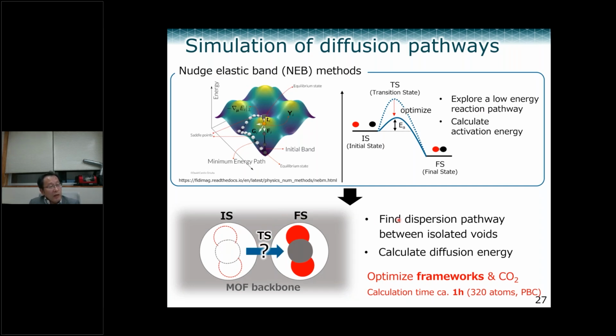And the point is, Matlantis can optimize not only the CO₂ position, but also the framework itself. If you use DFT and want to optimize the framework as well, not only CO₂, in this case the computer resource requirement is quite huge. But in the Matlantis case, you can easily do this kind of calculation. In this case, we spent just 1 hour for 320 atoms, applied with a periodic structure.